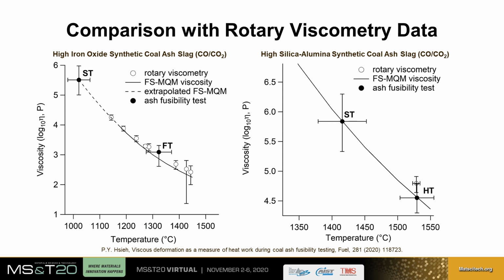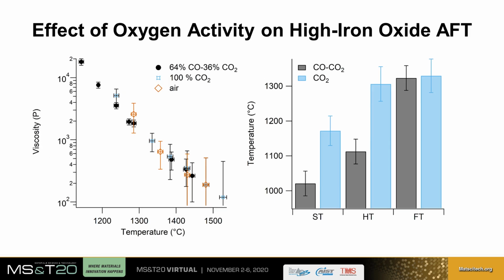The results for the reducing atmosphere case are shown in these two plots. Since no significant difference in AFT results was observed for the high silica and alumina sample, only data on the high iron sample will be shown on the next slide. Rotary viscometry of the high iron slag was repeated using a carbon dioxide atmosphere and again in air. An increase in viscosity at 1238 and 1285 degrees C were observed under inert and oxidizing conditions, respectively.